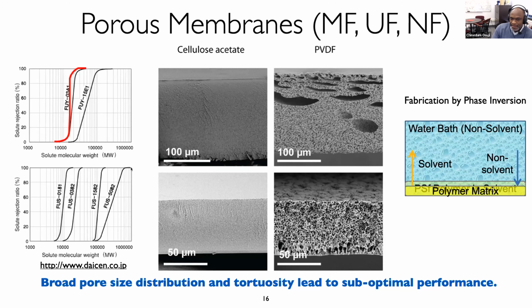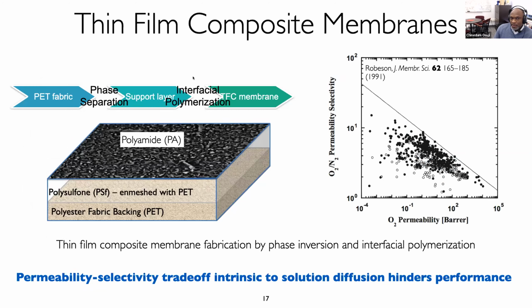Okay, and so membranes of this type can be made in very high volumes and for very low cost, but the structure that you get as a result has a broad pore size distribution and tortuosity associated with the transport that leads to suboptimal performance. Okay, likewise, thin film composite membranes that are used for reverse osmosis desalination, and looser forms of which are also used for nanofiltration, also have strong limitations in terms of permeability and selectivity that are associated with the distribution of transport regulating features in that system.